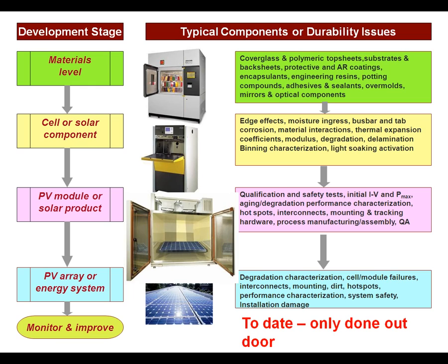At a PV module level, where you're looking at qualification tests, obviously you need a much bigger chamber that can house an entire module, and you'll be looking at qualification issues where you're doing initial IV curve tracing, checking to see what your Pmax is and other performance characterizations. You'll also, of course, be looking to see if there are any hotspot issues, any issues related to interconnects, bus bars, and so forth.